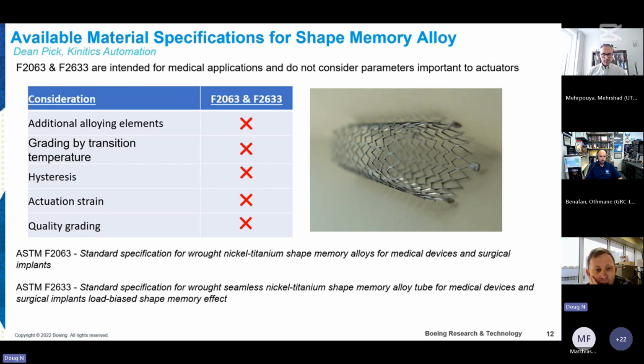It does take into account quality, but there's one quality grade, and it's pretty high quality. So F2063 does produce really good nickel titanium, but there may be scenarios where we want to accept a lower quality grade, because we might not need that high of a level for our specific application. I'll note just here at the bottom, I know I'm using the ASTM designations quite often. That's maybe a bad habit within the standards community. But I will note F2063 is the material specification for wrought nickel titanium for medical devices and surgical implants.